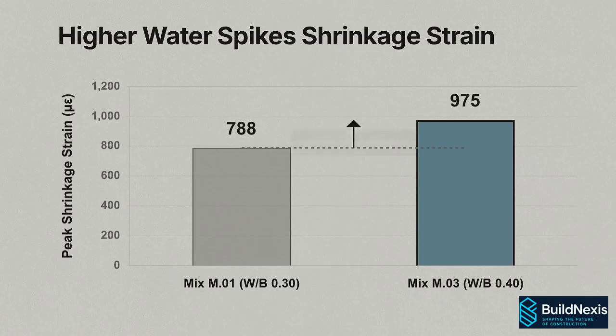This chart shows the peak microstrain recorded at the highly exposed top location across the different designs. Mix M.01 reached 788.4 microstrain. Mix M.03 peaked at 974.5 microstrain. That represents an approximately 24% increase in maximum shrinkage strain between the two formulations.